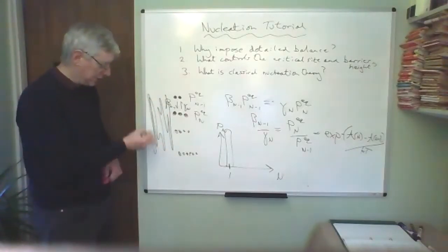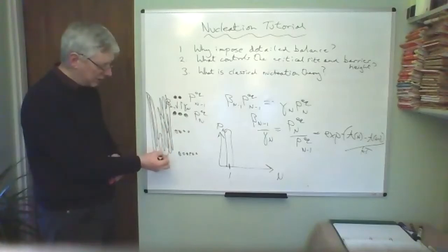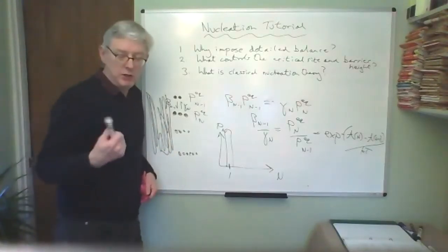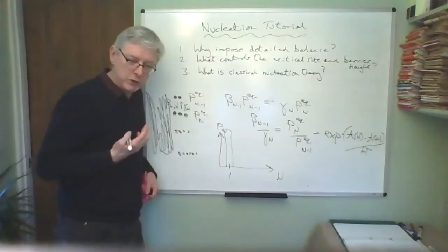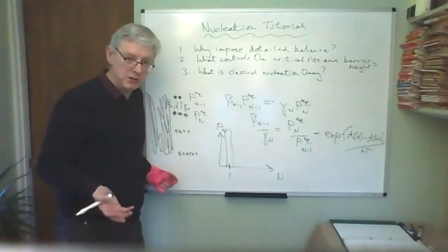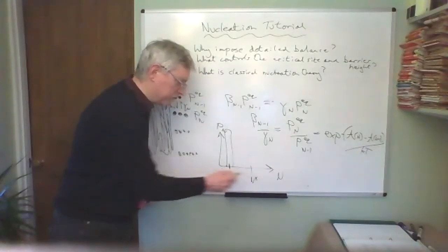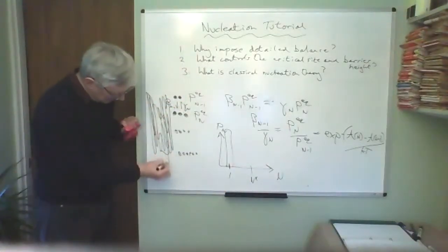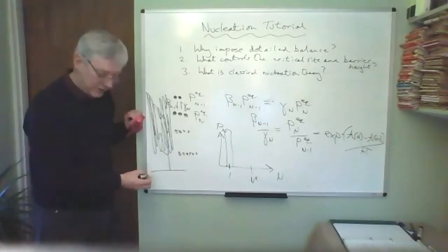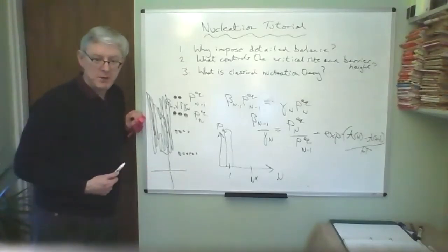This is time evolving as my pen goes up and down. The cluster is growing and it is decaying. And this defines what nucleation means. It means that one is waiting for an incubation period to reach a certain size, which is called the critical size. And once you reach that certain size, which might be, shall we say, here, then whoosh, it's all downhill.